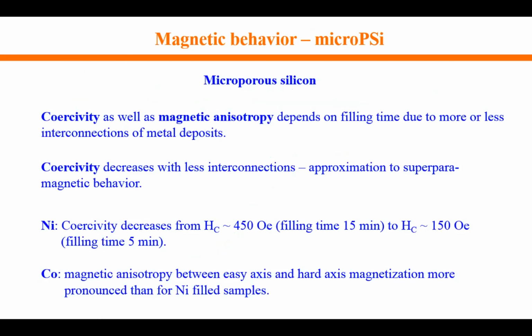So about the magnetic behavior of microporous silicon: the coercivity as well as the magnetic anisotropy depend on the filling time due to more or less interconnections of the metal deposits. The coercivity decreases with less interconnections and approximates a superparamagnetic behavior. In the case of nickel, the coercivity decreases from about 450 Oersted for a filling time of 15 minutes to about 150 Oersted for a filling time of 5 minutes. And in the case of cobalt, the magnetic anisotropy between easy axis and hard axis magnetization is even more pronounced than in the case of nickel samples.